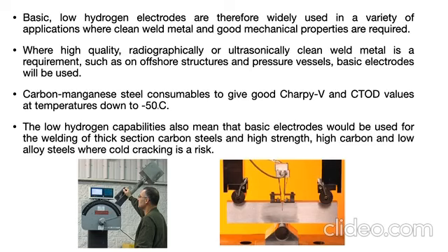The path through which the hydrogen tries to escape will eventually form a crack, and usually it is known as cold cracking because it happens after solidification. It is also known as delayed cracking because it takes some time for the hydrogen to escape and then form hydrogen cracking. So this is the main reason why whenever we do a radiographic test or any sort of test after a welding is performed,